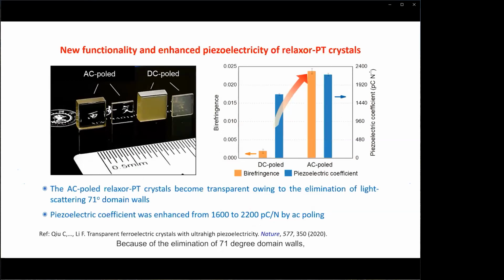Because of the elimination of 71-degree domain walls, the AC poled crystals become transparent as shown here. This is a very interesting observation and indicates that we can now incorporate optical functionalities into the high piezoelectric PMN-PT crystals. In addition, the piezoelectric coefficient was enhanced about 30% by AC poling when compared to the traditional DC poled samples.